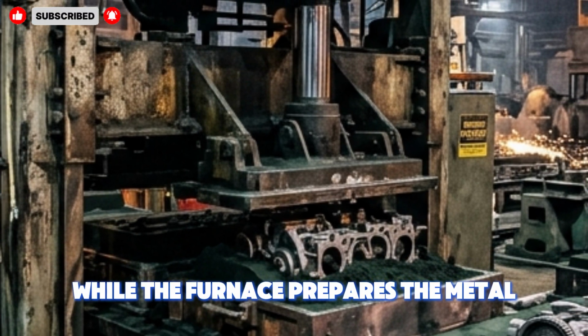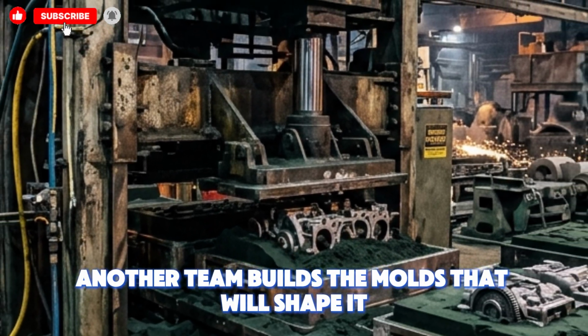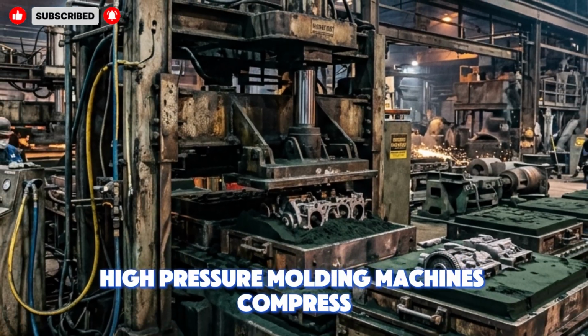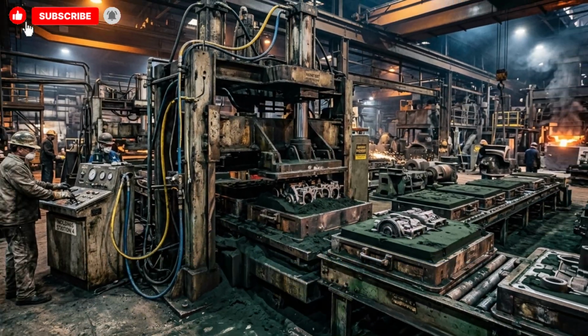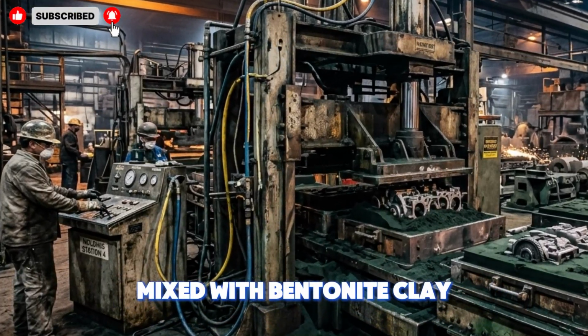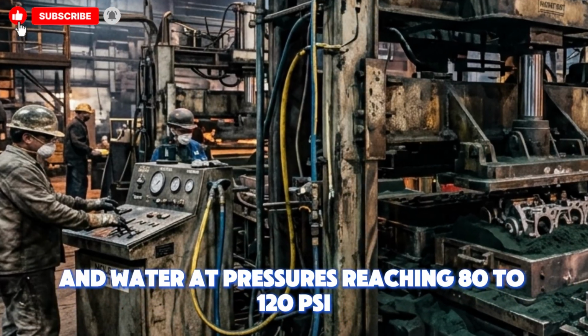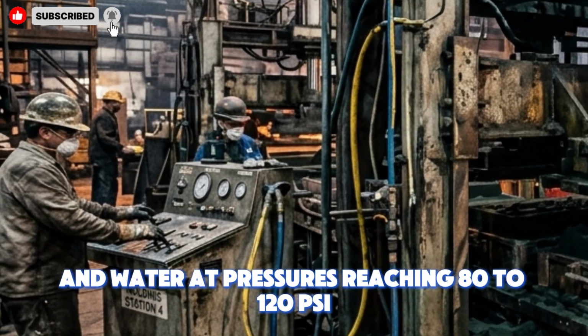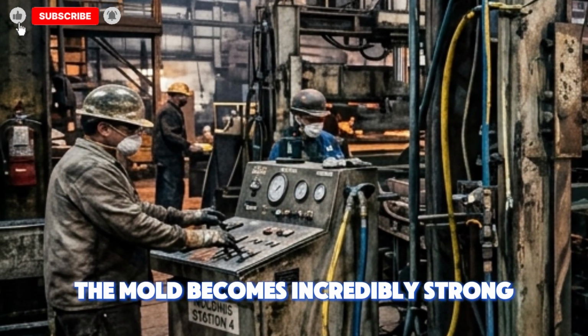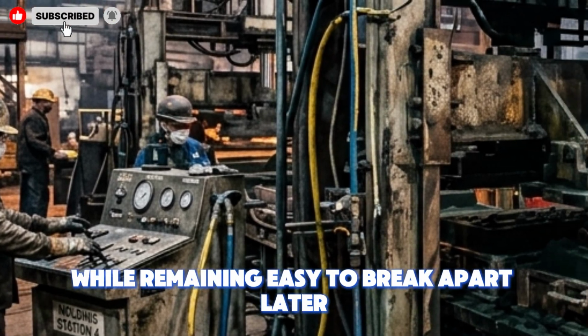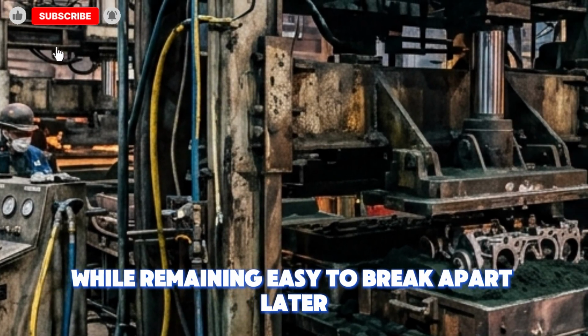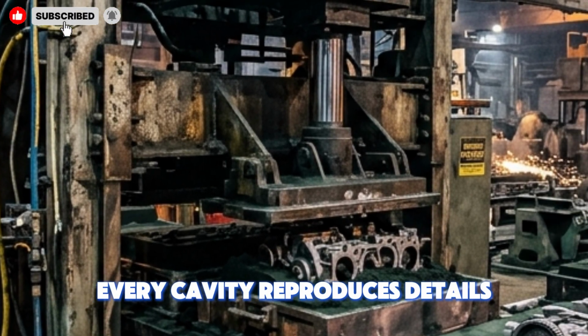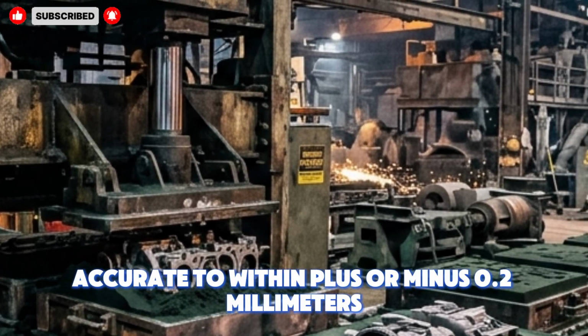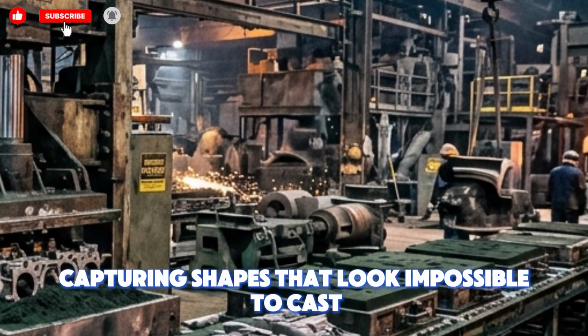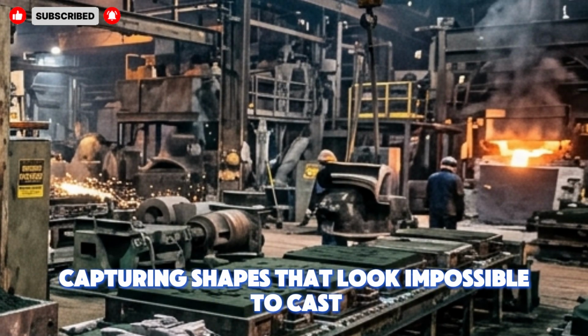While the furnace prepares the metal, another team builds the molds that will shape it. High-pressure molding machines compress specially prepared silica sand mixed with bentonite clay and water at pressures reaching 80 to 120 psi. The mold becomes incredibly strong, while remaining easy to break apart later. Every cavity reproduces details accurate to within plus or minus 0.2 millimeters, capturing shapes that look impossible to cast.